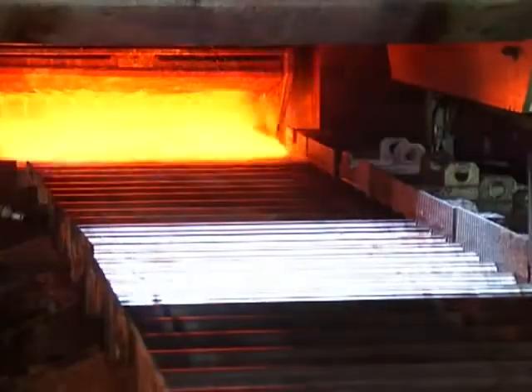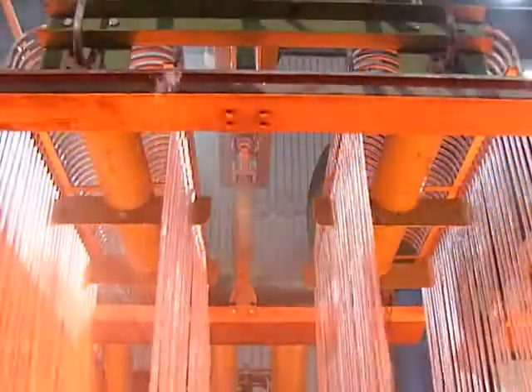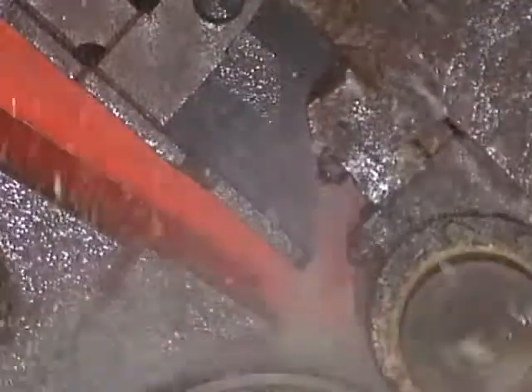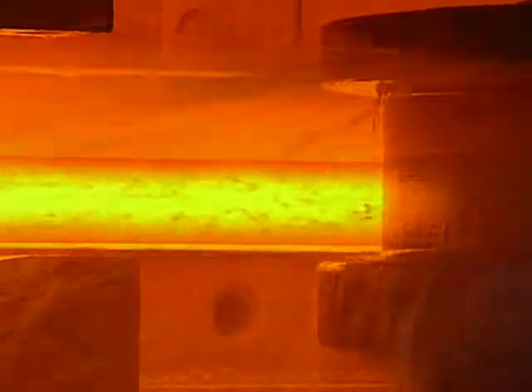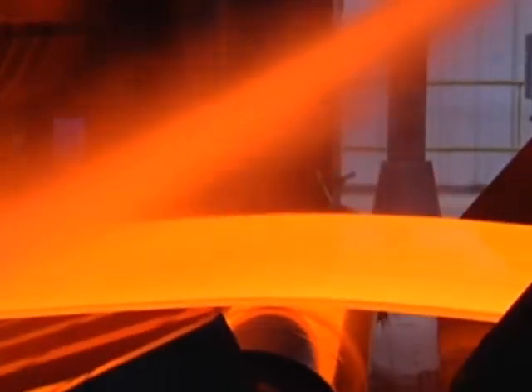The two strips are controlled in parallel in the mill by an automation system. Reduction of the rolling forces by the roll gap lubrication and simultaneous optimization of the rolling process for ultra-thin strip. Significant improvement in strip flatness so that re-rolling in the skin pass mill is not required for certain strips. Megasteel is now in a position to offer an enhanced, profitable product range which includes both thin strip and high strength grades.